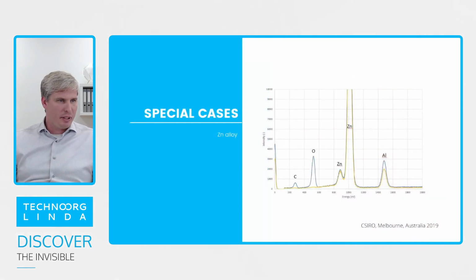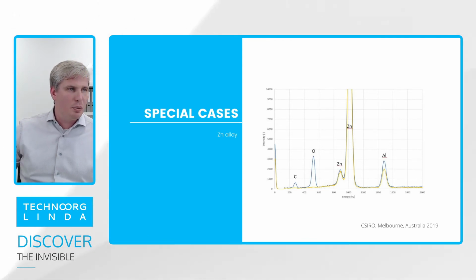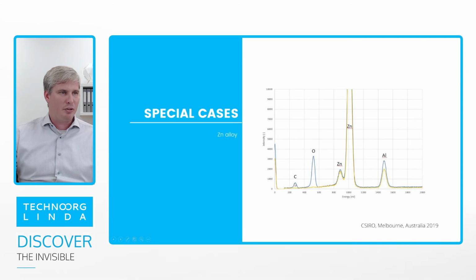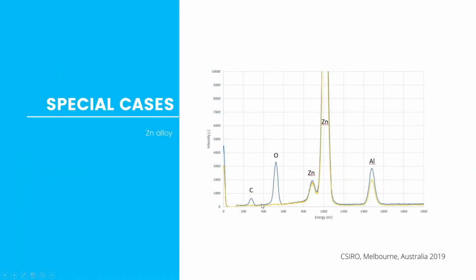Just to show you the difference between using or not using the VTU, there was a zinc alloy sample prepared by the group of CSIRO in Australia. Once they prepared it, but during the transportation they did not use the vacuum transfer unit. You can see the oxygen peak here. Next time they prepared the same sample, but the transfer was done by using the VTU, and you can see there was no additional oxygen and there was no oxide layer on the surface. Also, you can avoid carbon contamination or any kind of unwanted material on the surface.